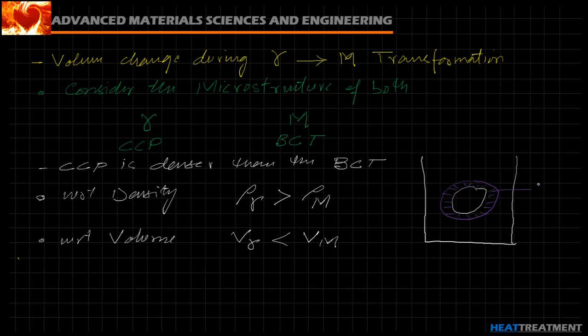This is the outer layer or shell, whereas still inside is austenite. We know that the inside tends to transform to martensite, and that is associated with the volume increase that is resisted by the already formed outside layer of martensite. And we know that this martensite is very hard and brittle.